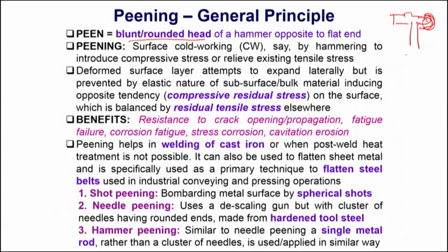When you deform the surface, you create a deformation zone underneath, and in a metallic material that zone is likely to develop a higher density of dislocations. Because of the recovery process, a residual stress is developed which is compressive in nature. This is the principle theme of shot peening: you apply limited surface deformation, the material deforms only to a very limited depth, and during recovery a state of stress is created which is residual and compressive — beneficial for many mechanical applications.